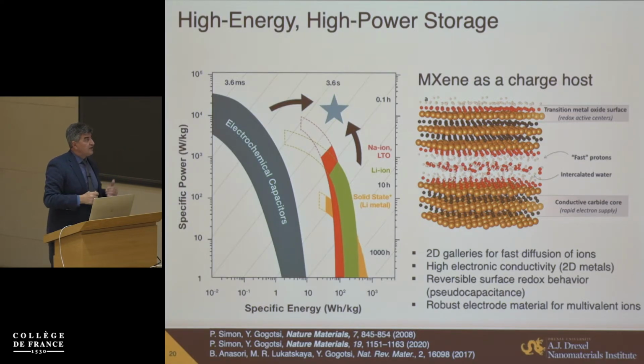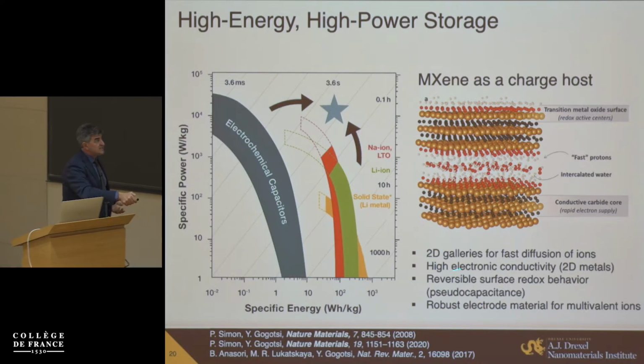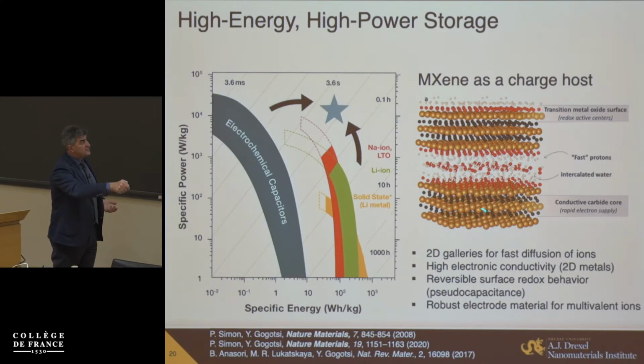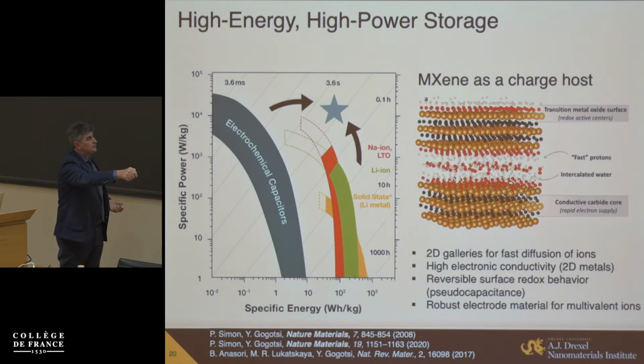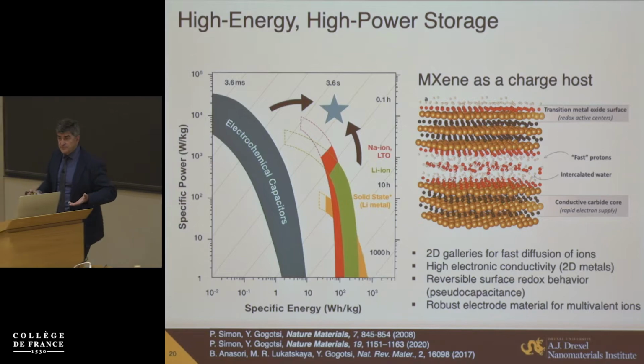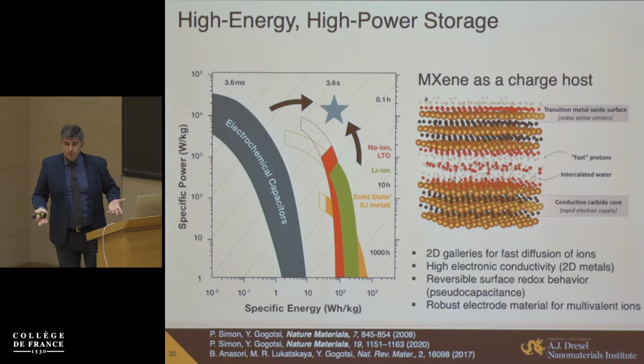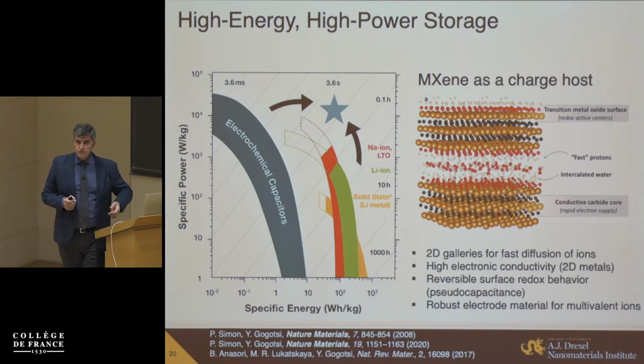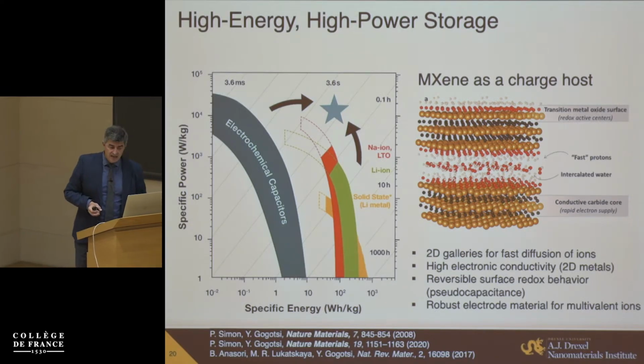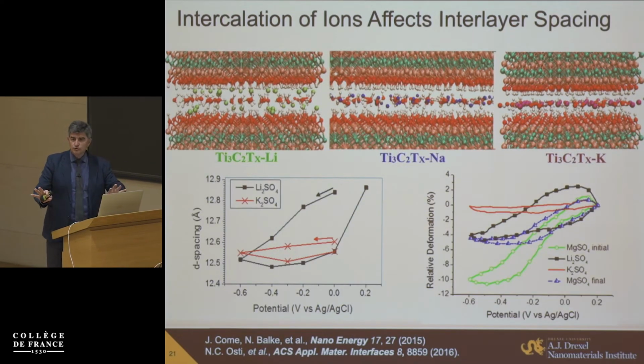And this is a game we are trying to play, using this in MXenes electronic conductivity to provide faster charging, using 2D galleries to provide fast diffusion of ions, using transition metals in various niobium, vanadium, moly, titanium to provide reversible surface redox reaction here. And also, because of this strength, because of these galleries, it's possible to squeeze zinc, magnesium, aluminum, and other multivalent ions here.